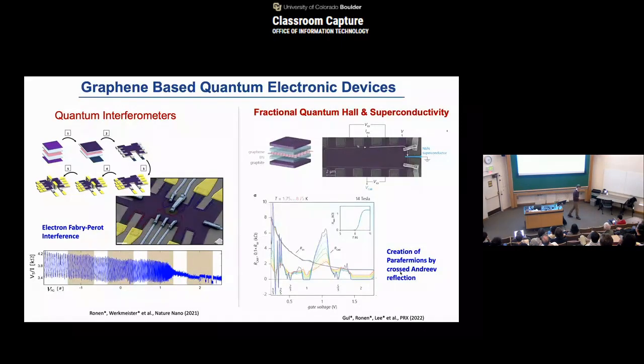Sorry about this, my intention is not to dwell on this slide, just to show that, hey, this is a capability, we can do that. In the same way, as another demonstration, unlike gallium arsenide, we can replace one of the electrical contacts with a superconductor. This is the superconducting electrode. Usually in semiconductors, it's very difficult to make a good contact with the superconductor, which is usually a refractory metal, because of Schottky barrier formation. Graphene has no gap, so we can make a good contact.